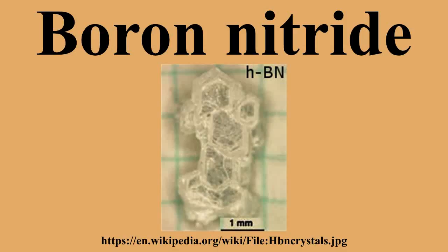However, the properties of BN nanotubes are very different. Whereas carbon nanotubes can be metallic or semiconducting depending on the rolling direction and radius, a BN nanotube is an electrical insulator with a band gap of 5.5 electron volts, basically independent of tube chirality and morphology. In addition, a layered BN structure is much more thermally and chemically stable than graphitic carbon structure.